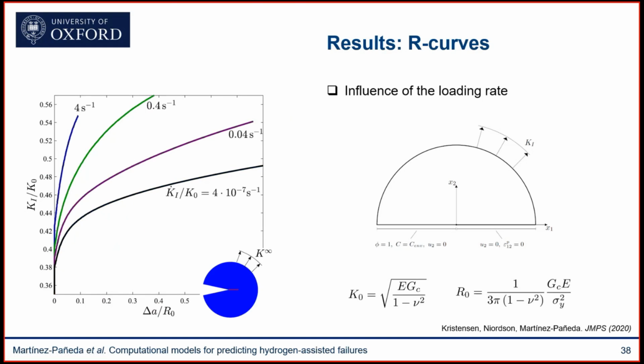Here I'm showing another classic experimental observation, which is the influence of the loading rate. We know that if we load our samples very fast, there's not enough time for the hydrogen to distribute within our sample, and therefore we get less embrittlement. But if we load very slowly, then we have more hydrogen distribution within the sample, and this brings a reduction in the crack growth resistance curves, as you can see here.